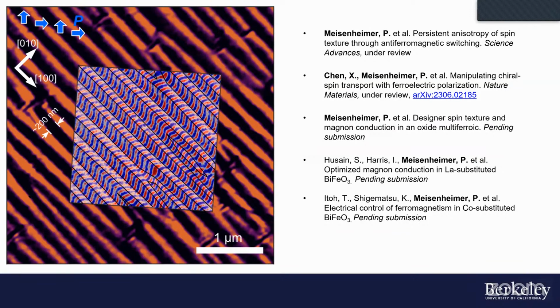They very likely come from either mechanical or crystallographic defects in the film. Yeah, absolutely. When your structure is very nice and perfect, you get this stripe-like domain pattern. But as you start to frustrate it and move away from the anisotropy of the substrate, it'll break up into what we call 4-variant textures, which is kind of what's starting to happen here.